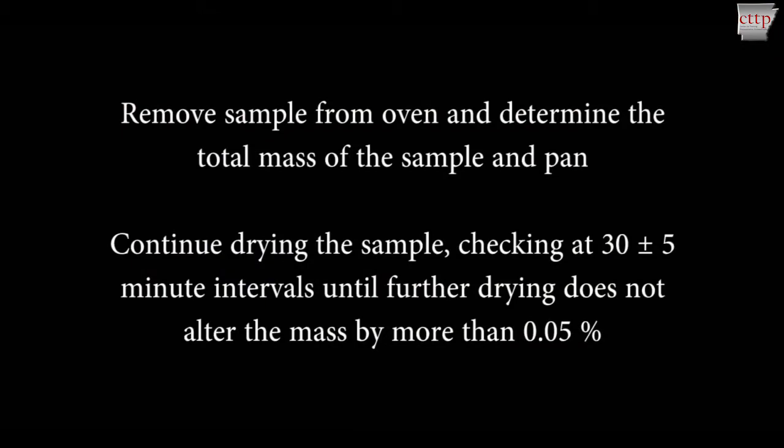Dry the sample, checking at 30 plus or minus 5 minute intervals. Remove the sample container from the oven and determine the total mass of the sample and pan. Calculate the mass of the sample by subtracting the mass of the pan. If the mass has not changed by more than 0.05 percent, the sample is considered dry.